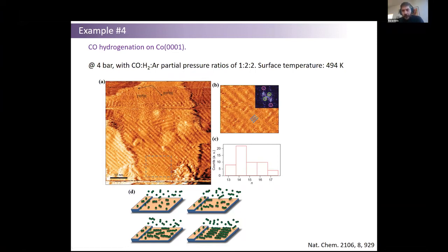Now we know for a fact from reaction studies on cobalt nanoparticles that the surface is active in producing methane in the first 2 minutes, which is completely undesired. But after 2 minutes, the selectivity switches from methane to desired long chain linear hydrocarbons. So the model here suggests that the terraces are active in formation of methane, whereas the step edges can also do CC coupling. So that's where linear hydrocarbons start to form.